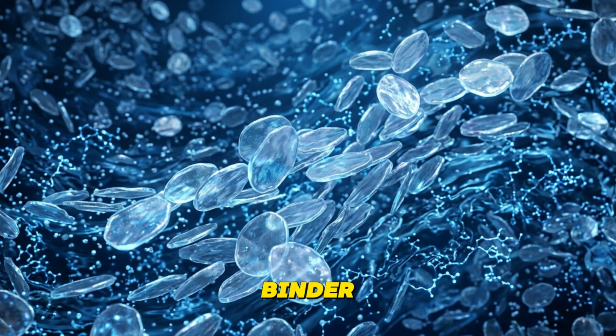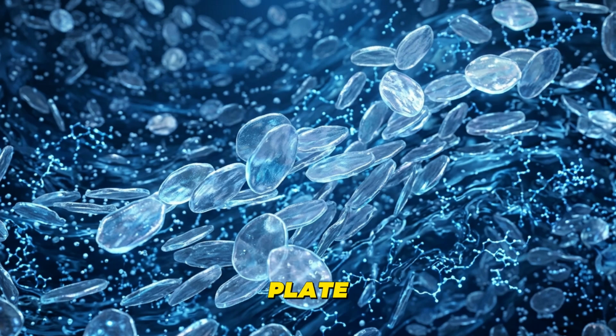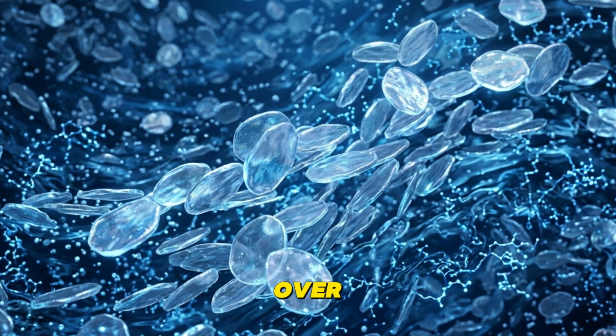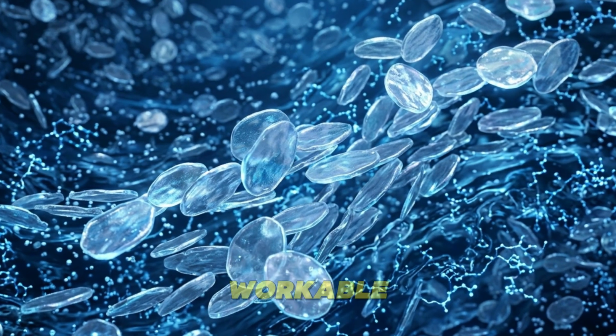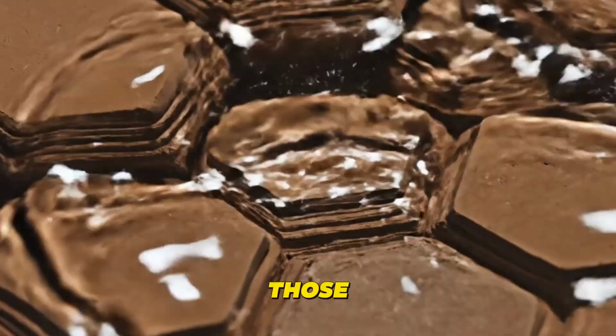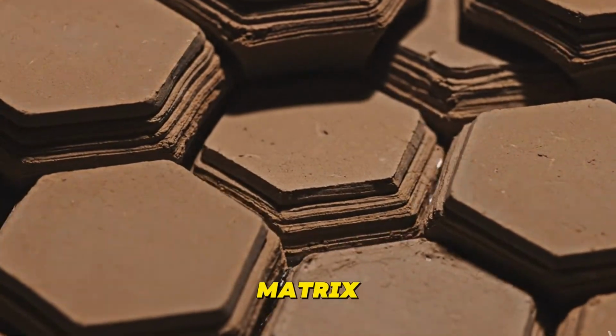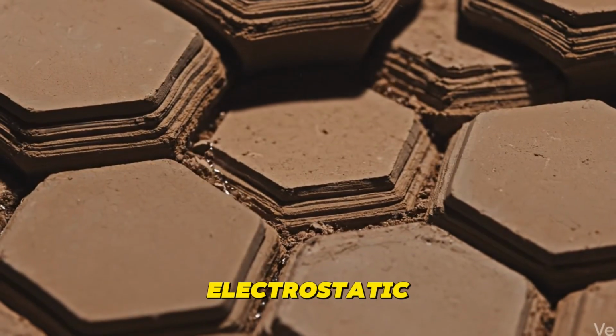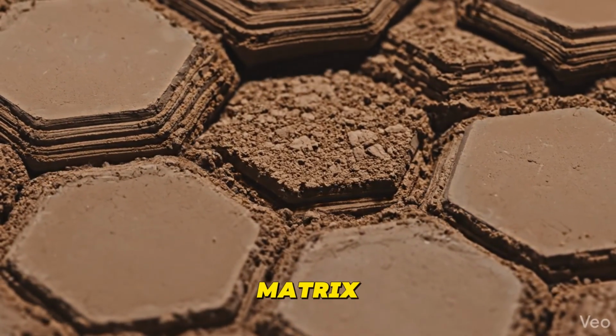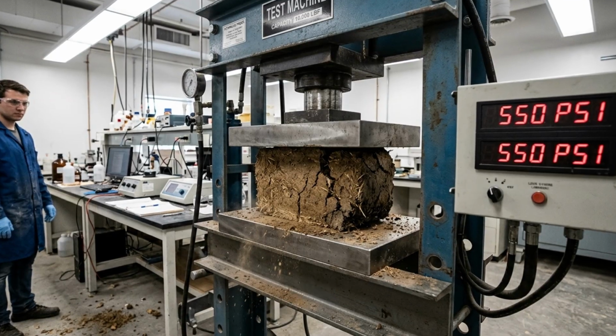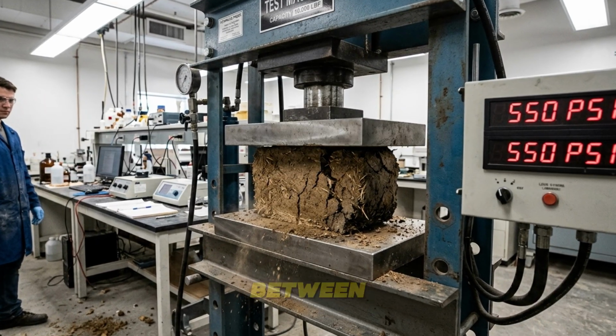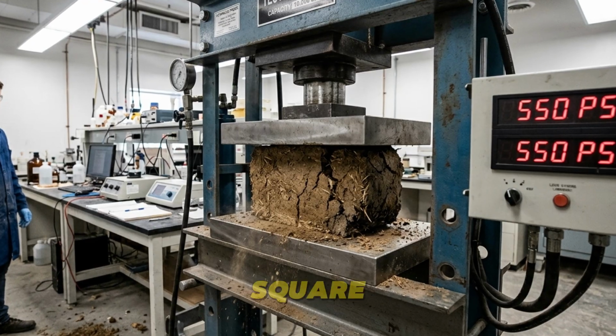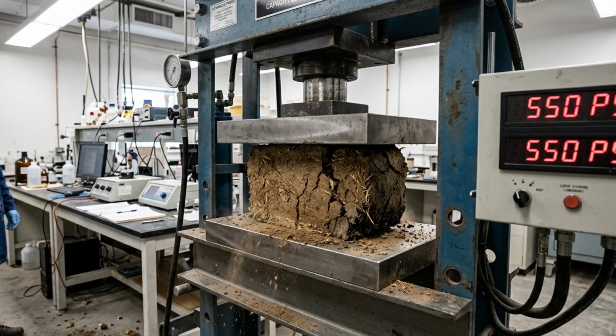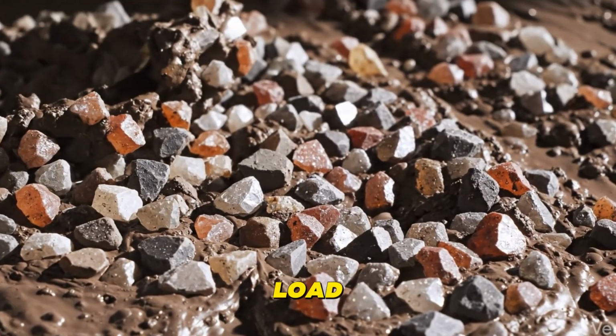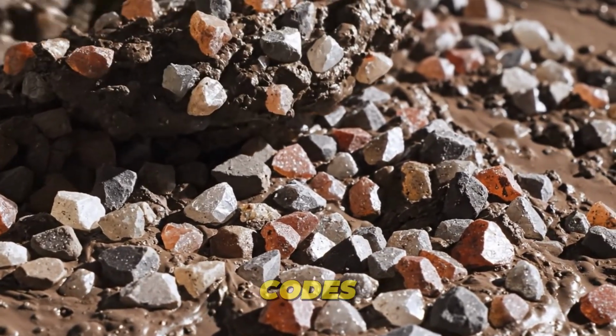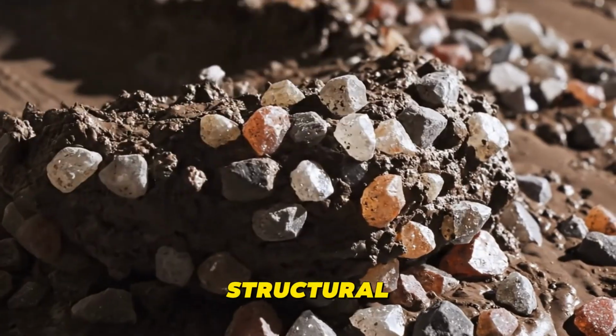Clay is the binder. When wet, clay particles, which are plate-shaped at the microscopic level, slide over each other, making the mixture plastic and workable. As the clay dries, those plates pack together and form a rigid matrix through surface tension and electrostatic attraction. The dry clay matrix is hard, dimensionally stable, and has significant compressive strength, typically between 300 and 600 pounds per square inch in a well-mixed cob, which exceeds the compressive strength requirements for a load-bearing wall in most residential building codes. Sand is the structural aggregate.